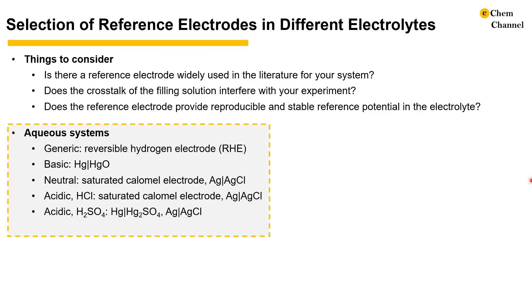Next, we are going to provide examples of common reference electrodes in three-electrode systems. In aqueous electrolytes, the most generic reference electrode may be the reversible hydrogen electrode (RHE). Researchers know well how its potential varies as a function of pH against the standard hydrogen electrode, making it a good reference in aqueous electrolytes. Mercury/mercury oxide is a good reference in basic electrolytes. The saturated calomel electrode and silver/silver chloride are the most common in neutral and acidic electrolytes. When sulfuric acid is used, mercury/mercury sulfate is a good reference electrode.